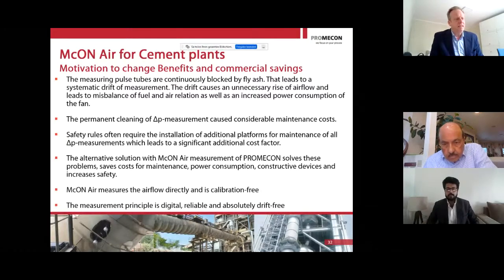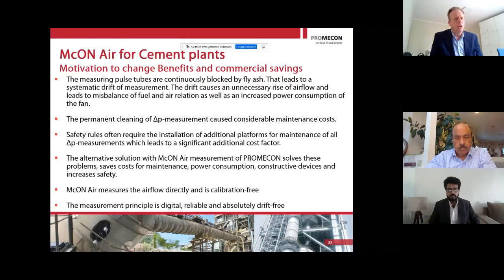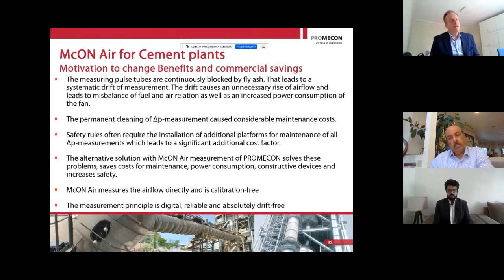In cement plants, the dust load is so high that delta pressure measurements usually clog up in a very short time. And also other systems that use, for example, heat dispersion, like a hot wire anemometer, they drift. Ultrasonic systems, especially in hot gases, are usually not even capable of shining through the duct because the gas density is so low and the dirt amount is so high.